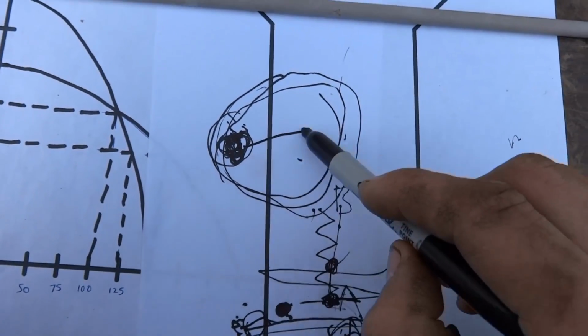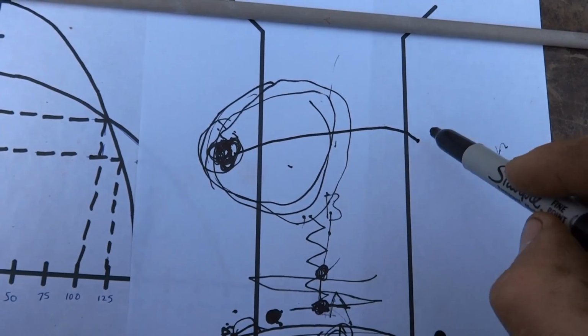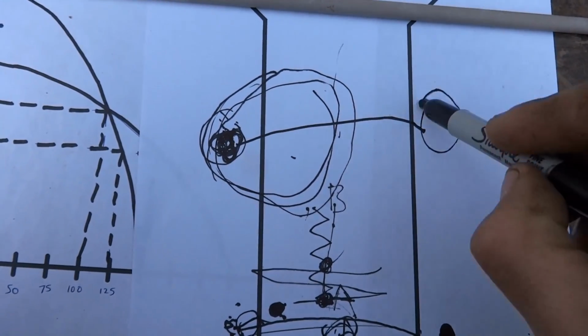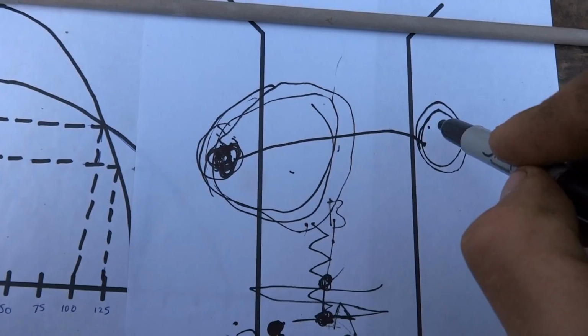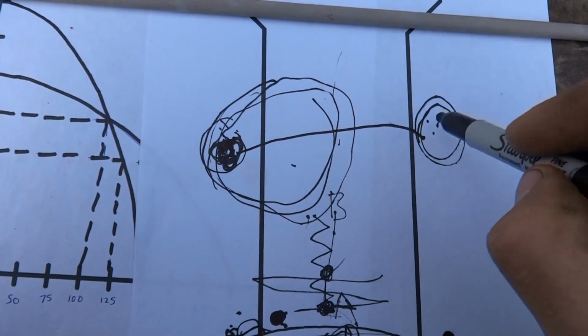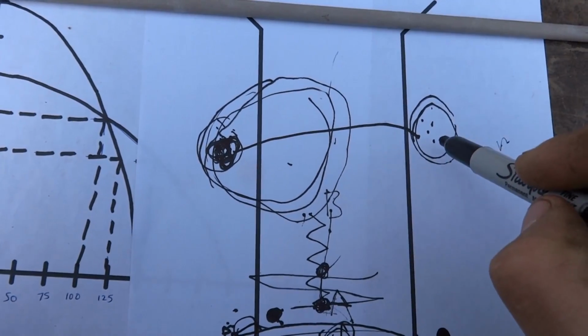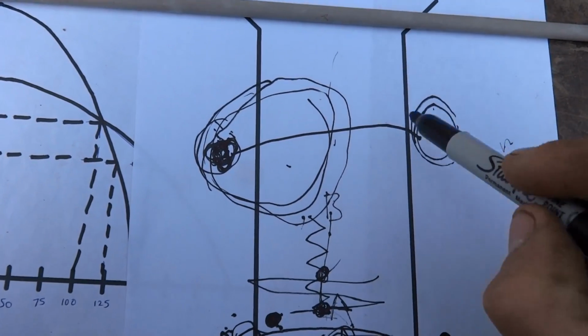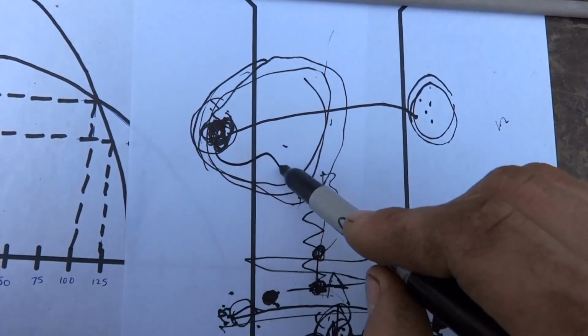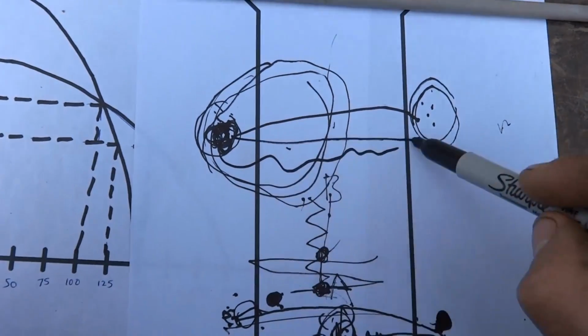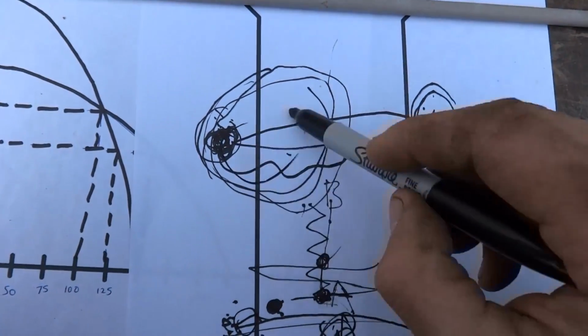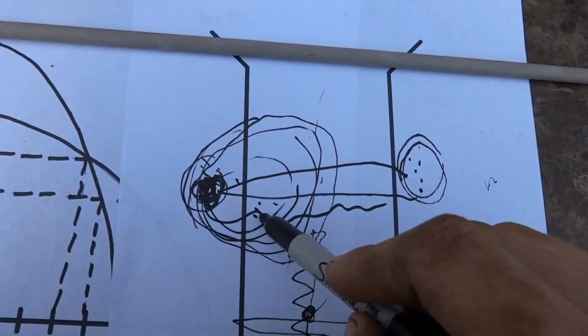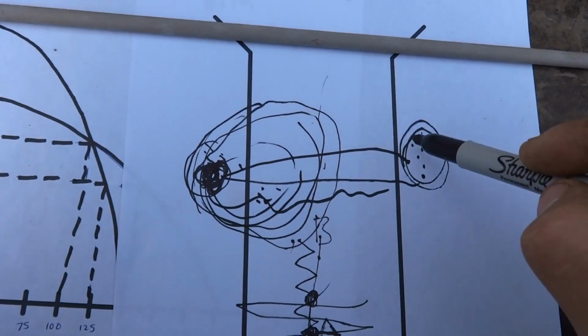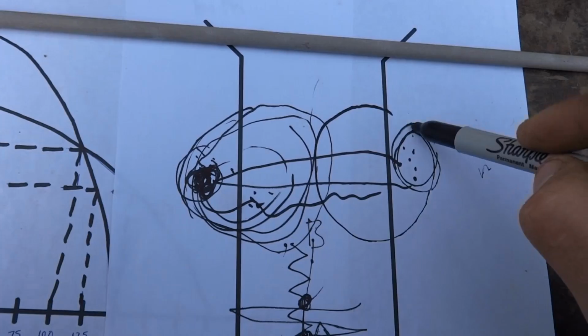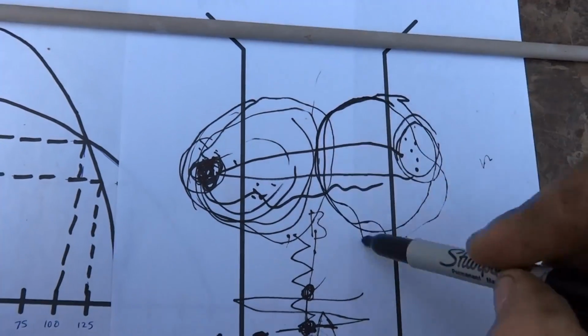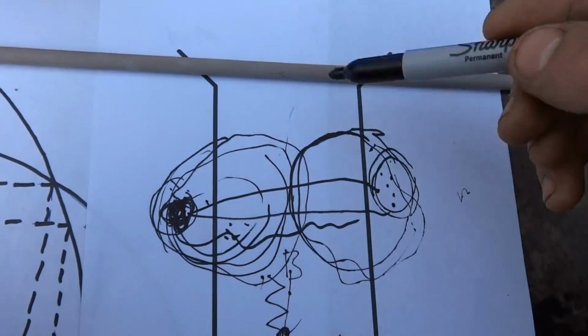He moves from the left-hand side over to the right-hand side. He holds a tight arc into the side bevel there. The very second he holds a tight arc, amperage increases, burn-off rate increases, voltage drops off, lack of voltage chills out the puddle. The left-hand side here starts to solidify. He's over at the right-hand side. The left-hand side has solidified. He's content with the amount of fill that he just deposited on the right-hand side, and he deposits a lot of metal on the right-hand side. He wants to stack metal.